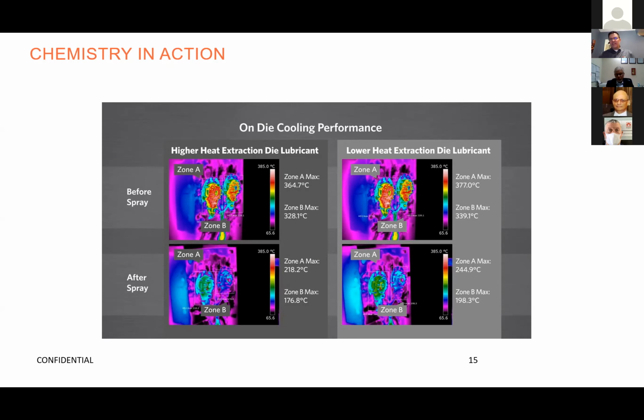One final point on this: often if you run a trial with putting a higher performing material on it, if you try to just start running that trial without changing any process parameters, it's going to fail, because we get so much more cooling. Then you're going to get more porosity because the die is too cold. You're not going to have shiny parts, you're going to get more staining. So it's all about getting the technology in there to optimize the process.